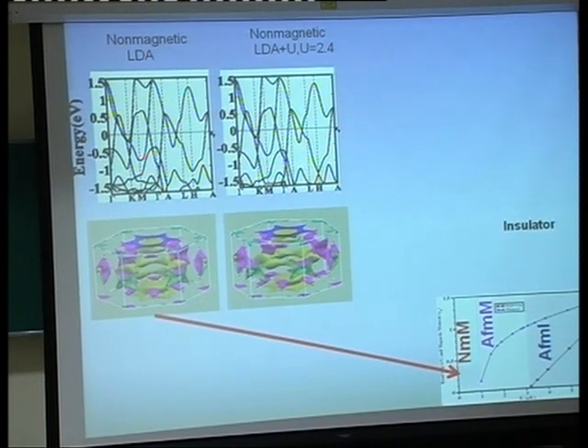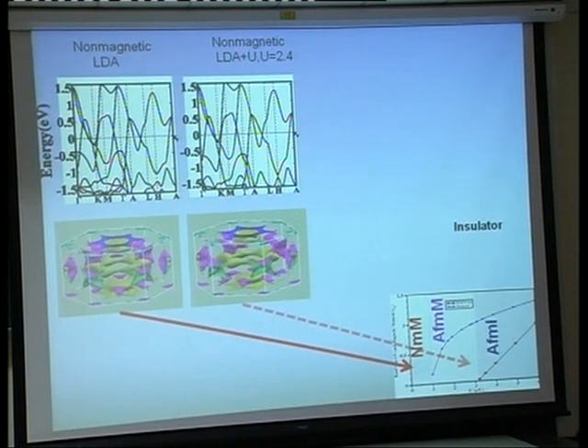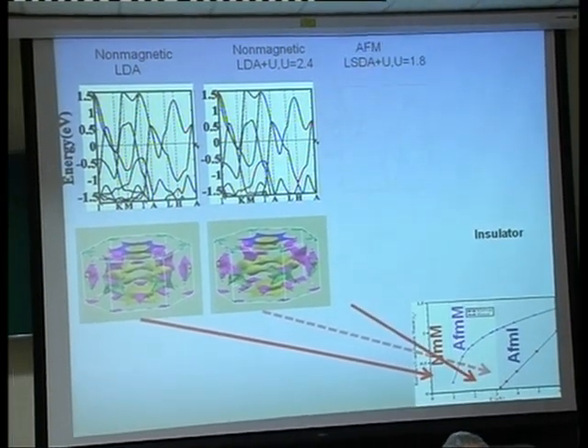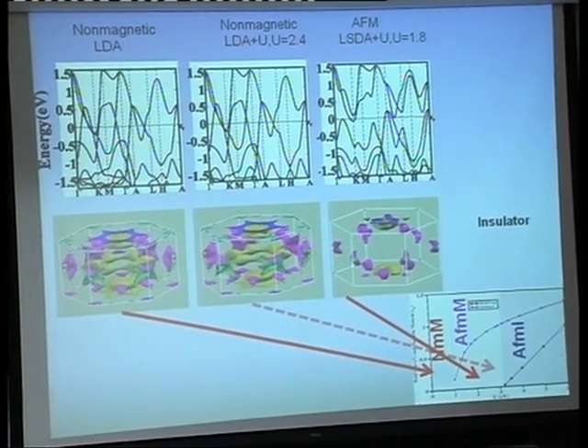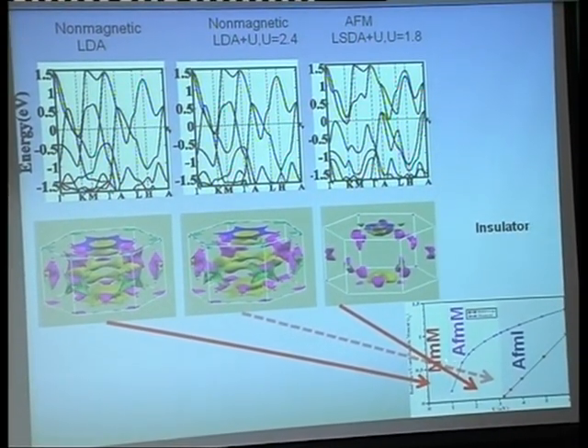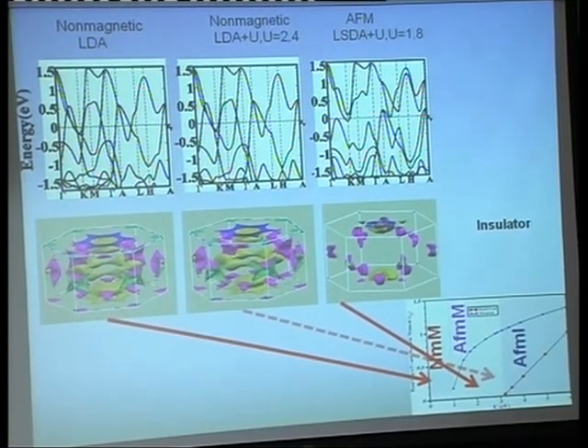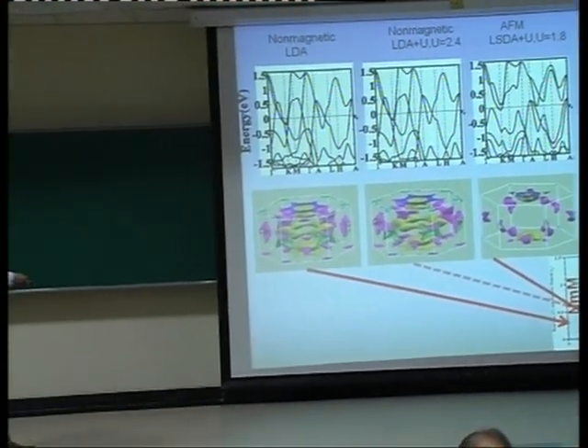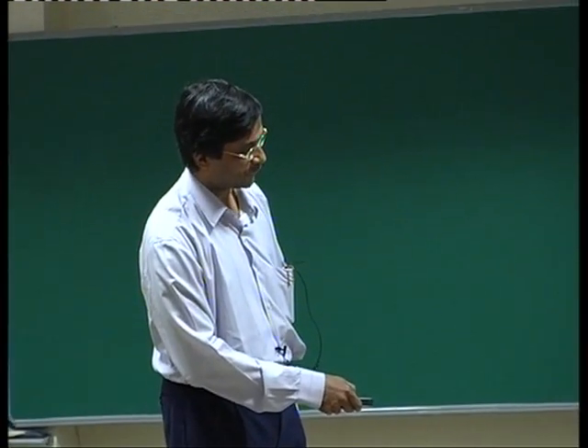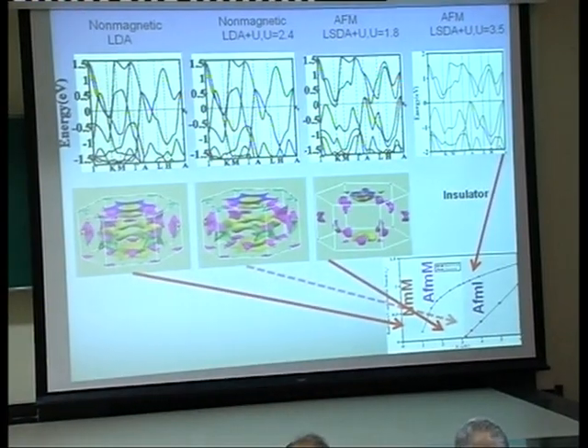If I increase the U value that I showed you already to 2.4, I get into that part, that is the metallic solution, but I have shown it as a dashed line because this is not the lowest energy state. The lowest energy state electronic structure looks completely different, and that's shown over here. And you can see what the Fermi surface looks like, and that dominates this antiferromagnetic metallic state. That's why this is an antiferromagnetic metal. This would have been a paramagnetic metal here, but across this boundary, the antiferromagnetic metal becomes more stable and the non-magnetic metal becomes more stable on this side. So there's a first order transition across here. And then if I increase the U value further, then I get into this insulating state over here, as shown over there. Now before I explain further, I would like to go back and make some schematic drawings.